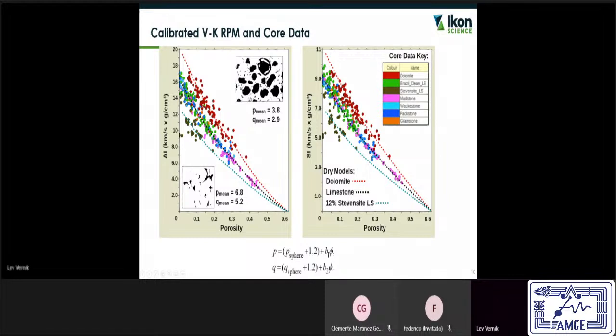These are the images that we actually analyzed, and we showed that this specific limestone here, with this type of pores and certain porosity, has a pore shape factor ranging from 3.8 for P waves to 2.9 for shear waves. They are visibly close to each other, and they are slightly greater than or more compressible than spheres. Of course, we see that they are deviating from the spheres.